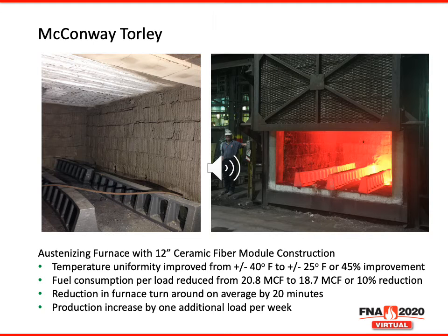At McConway & Torley in Pittsburgh, Pennsylvania, they utilize an austenitizing furnace with a 12-inch ceramic fiber folded module construction. A ceramic coating was applied at approximately 1/8 of an inch thick to the hot face of the fiber lining. After coatings were installed, the temperature uniformity improved from plus or minus 40 to plus or minus 25 degrees Fahrenheit, or a 45% improvement.